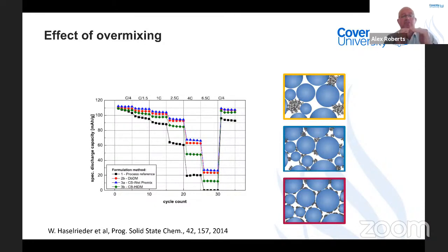If your cells tend to drift apart and your spread of data gets much wider at the higher rate, it could indicate that you maybe need to look at your electrode production again.